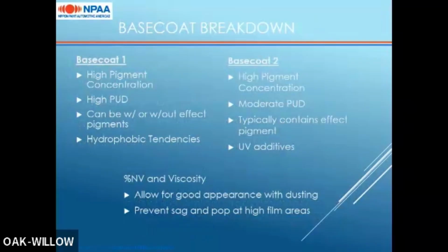Then just information on the base coats themselves. Base coat 1 is designed with high pigment concentration, again for that light protection. It has a high loading of polyurethane dispersion. It can be made with and without effect pigments, depending on what the desired finished color position is intended to be. It also is designed to be more hydrophobic, so even though it is a waterborne coating, it's designed to be hydrophobic primarily to ensure good compatibility with base 2 without them blending into each other.